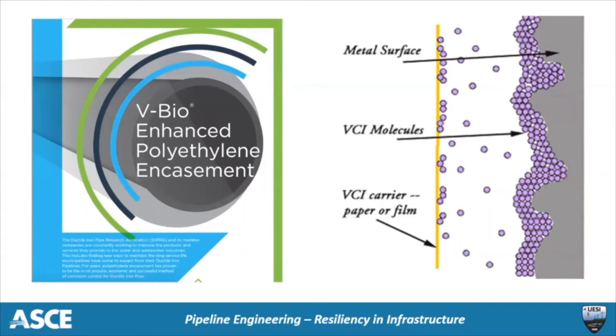Today, we recommend using an enhanced polyethylene film, V-Bio enhanced polyethylene, taking advantage of co-extrusion technologies in the manufacture of polyethylene film. We are able to introduce a corrosion inhibitor and an antimicrobial component that are infused in the innermost 1.5 mils of the film.